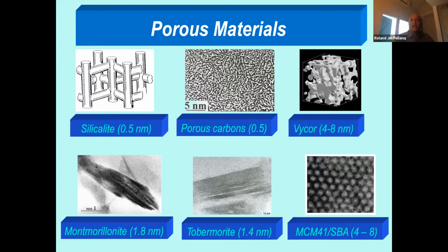Now let's go bigger in terms of pore size, and then you end up considering those porous glasses like Vycor, same like silicalite, purely silica. Pore size kind of messy, connected in 3D, but with a pore size distribution that's not very wide. The pore size of Vycor is typically in the range of a few, say 4 to 8 nanometers.